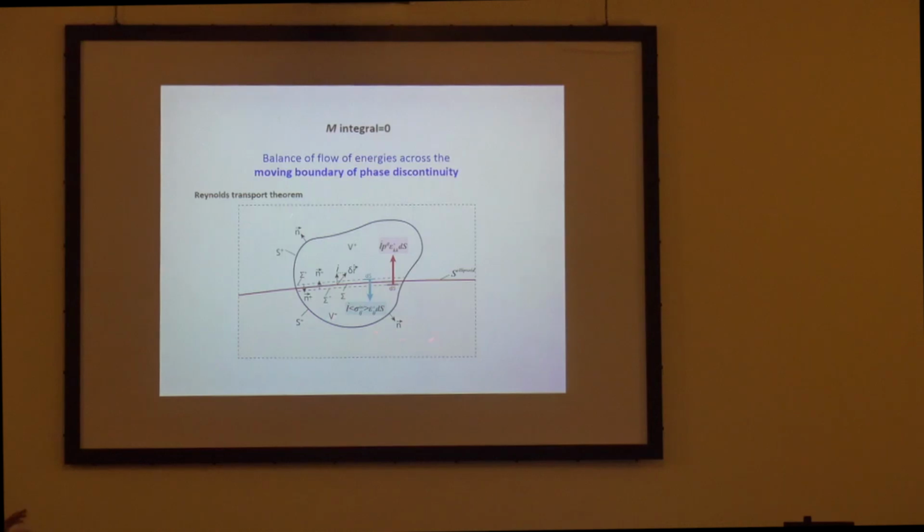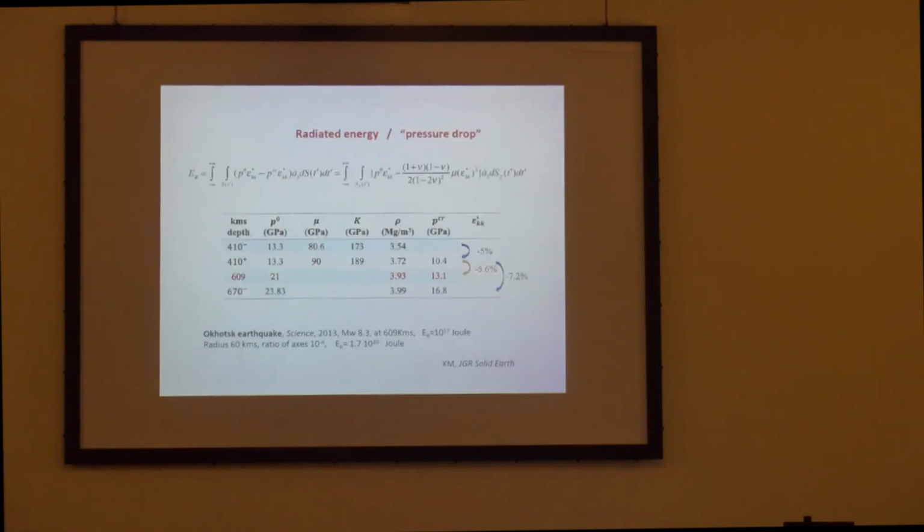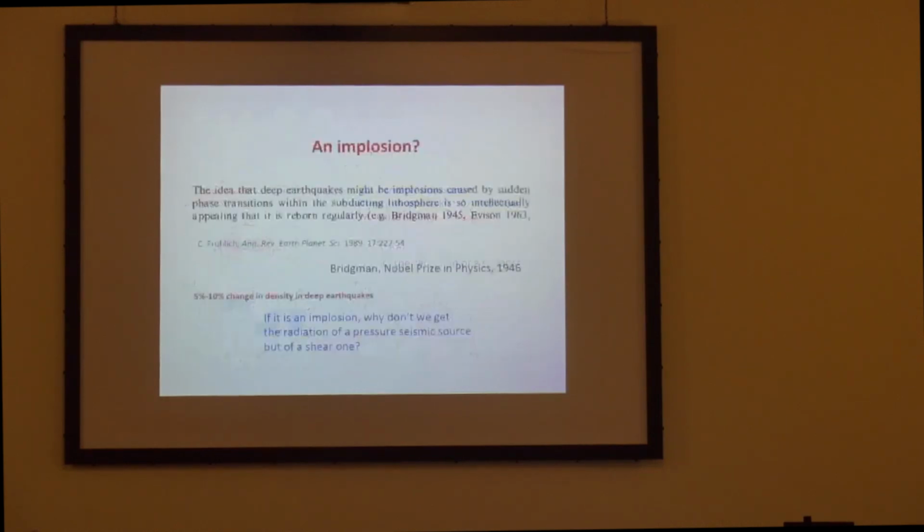Actually, in the Eshelby thought experiment, when the element is put back in the inclusion, and that I showed you before, and it is left to relax, then energy is extracted from the matrix into the inclusion. So there will be this energy that is extracted from the matrix into the inclusion, but the applied loading will produce that. With this, we can obtain the radiated energies.